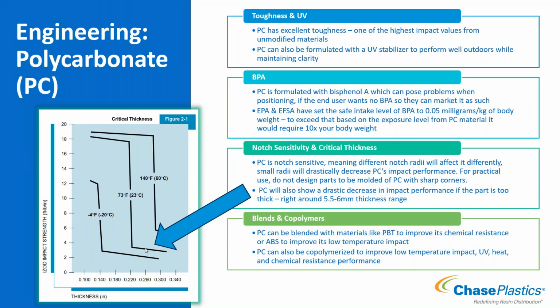And then lastly, some other variants of polycarbonate. Blends are a common thing done with polycarbonate. You might blend it with PBT because you want to improve the chemical resistance of polycarbonate. Polycarbonate by itself really doesn't have great chemical resistance, so maybe we blend it with PBT to improve that.